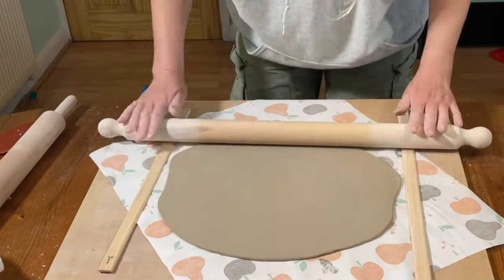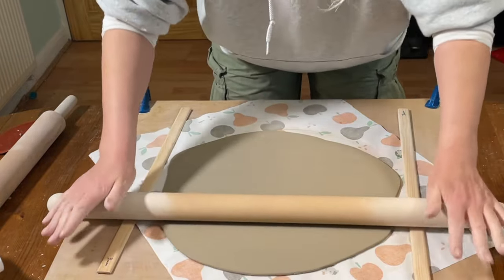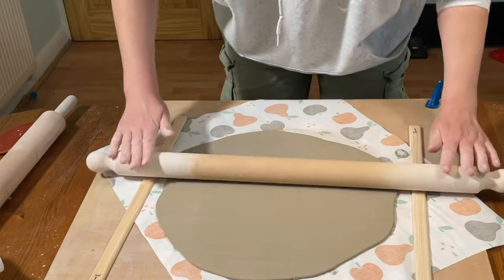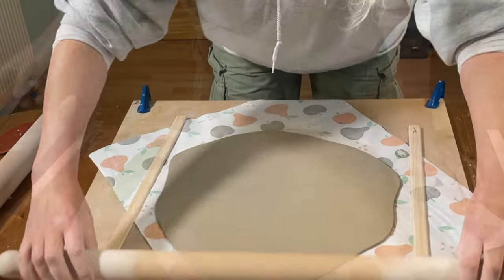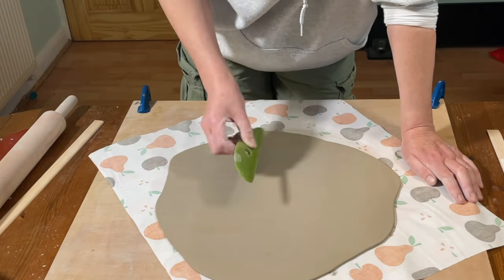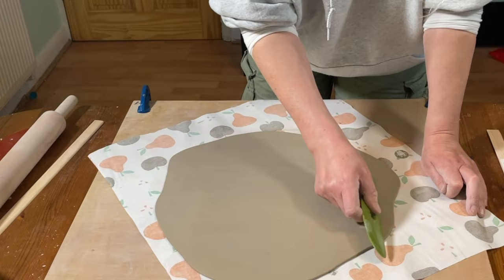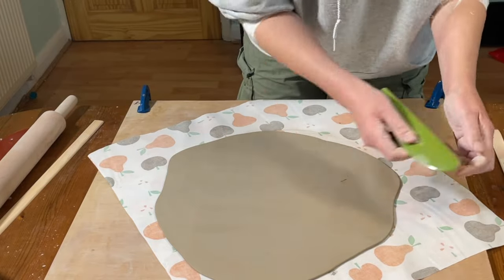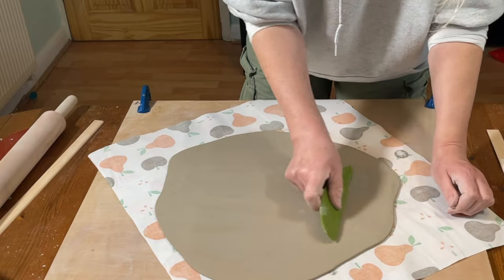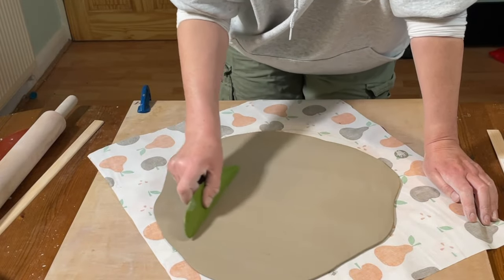When the clay reaches a certain size I start using roller guides, which make sure that the slab is an even thickness. I've switched to an even wider rolling pin — I'll put a link in the description below where I get them from. It's a UK company but they ship internationally. They're actually pasta-making rolling pins, the largest ones I could find. It's also important when you finish rolling the slab to compress it using a rib tool — either a rubber rib or a platter tool — as a way of aligning the clay particles and giving the slab extra strength. It also removes any texture left behind by the rolling pin or the surface.